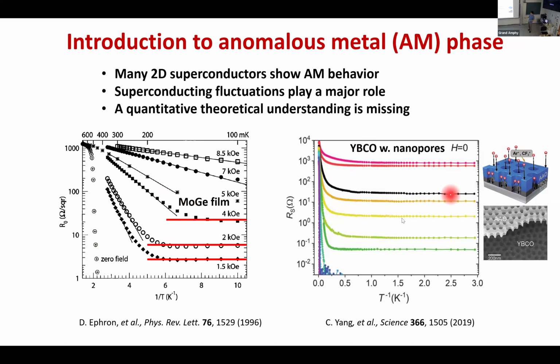And now even in, for example, high temperature superconductors, when they dig these holes to mimic Josephson junction arrays, they also see this without field, just by changing the size of the holes. Then they also see the saturated resistance after the superconducting transition.